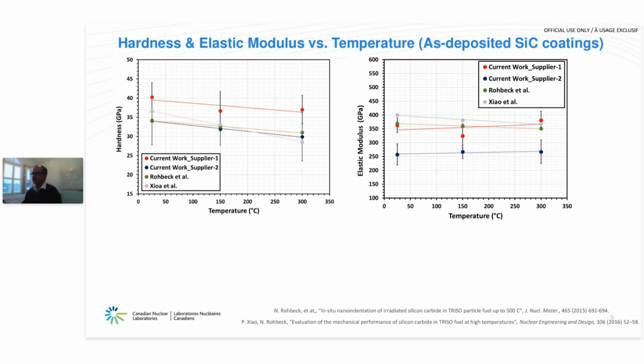In the elastic modulus results with temperature on the right, the supplier 1 particle, again in the red solid circles, over the temperature range, we don't see much of a change in the elastic modulus, and it was of the order of about 350 GPa for the coatings from supplier 1. The material itself has very high melting temperatures, about 2800 plus degrees C. I was expecting to see a slight drop in the elastic modulus over 300 degrees C, but our experimental measurements do not see the trend. I'm not sure. I'm just speculating.